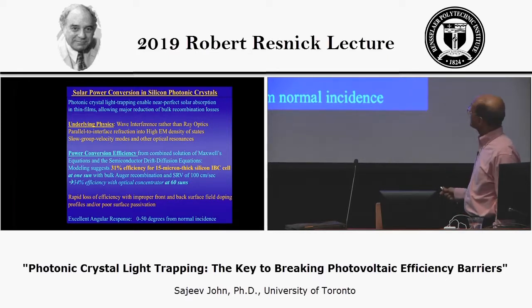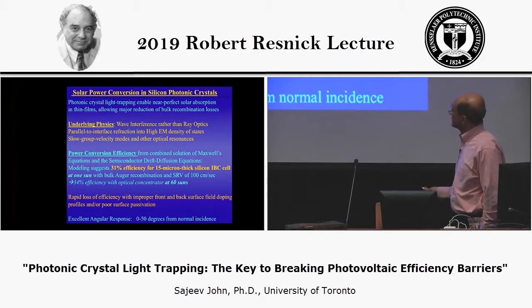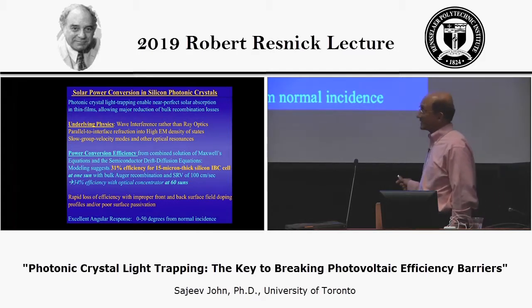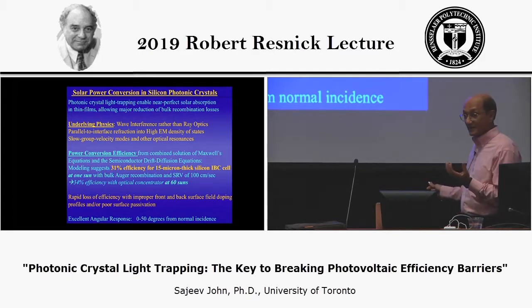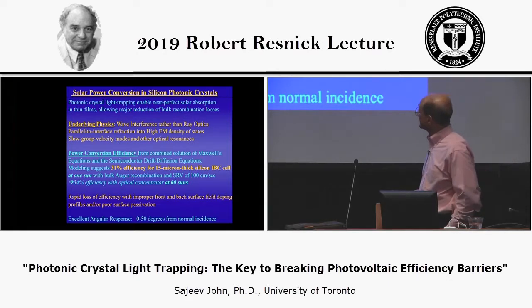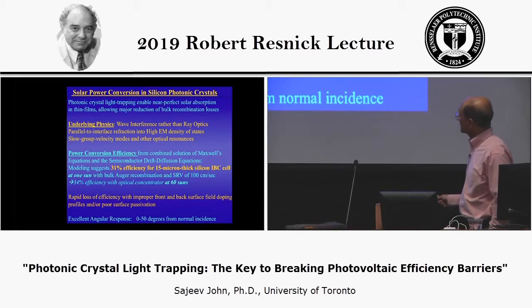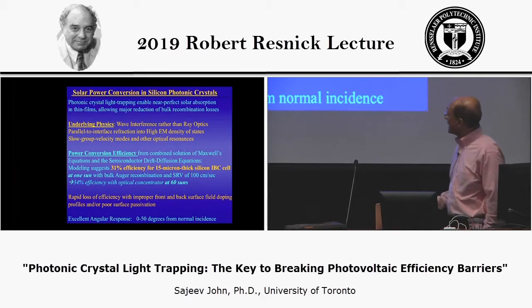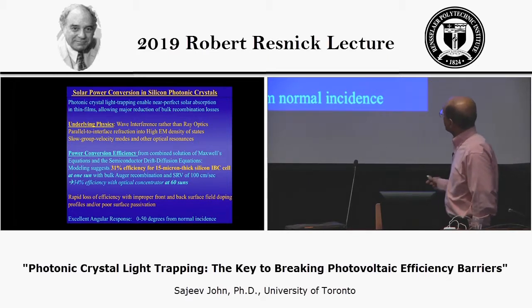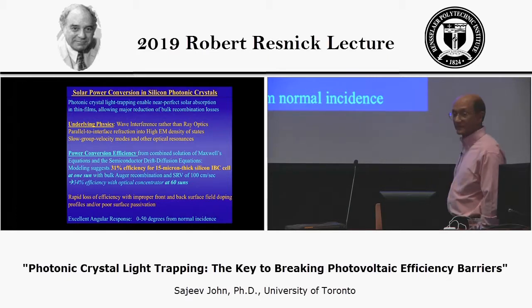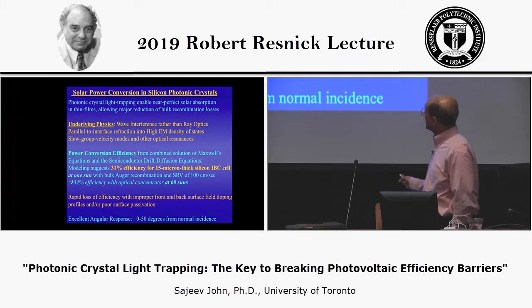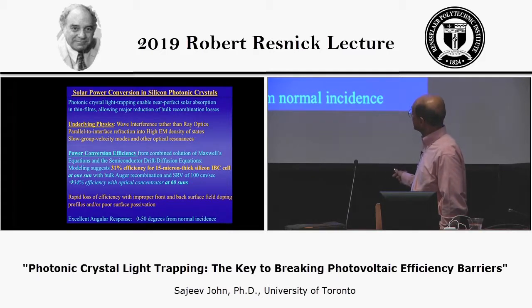And from this combined solution of Maxwell's equations together with semiconductor drift diffusion equations using state-of-the-art recombination models, the modeling predicts 31% efficiency at one sun with up to a surface recombination velocity of about 100 centimeters per second. And one thing I didn't mention is that if you go up to a concentration of 60 suns, this efficiency actually goes up to about 34%.